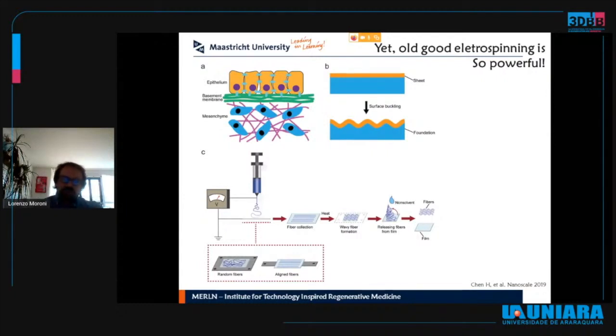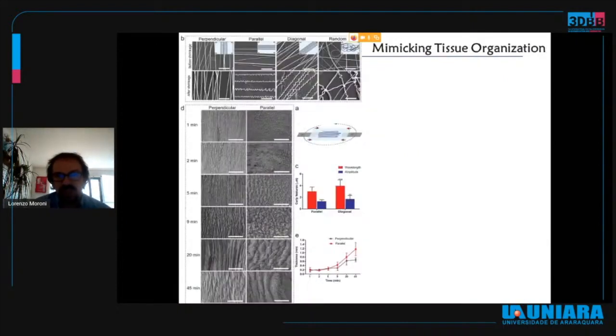So to solve this possible problem, we adopted a simple method where we would spin on top of a pre-stretched film, which then would be left to unstretch, and by doing so create a sort of buckling effect on the electrospun fibers, which would result in this kind of waved pattern on the fibers. So indeed, if we do this now, in a cartoon with real polymers, we did see an increase in the waviness of such fibers, not only on single fibers, but also, if you spin for long enough, up to 45 minutes, also at the mesoscale on the actual fiber mesh itself.